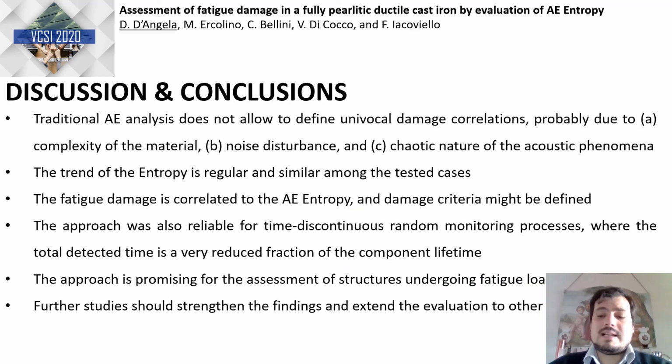Finally, we can discuss the results and trace the conclusions. We didn't show the results related to the acoustic emission analysis, but we can say that they didn't allow us to define a univocal damage correlation. This is probably due to the complexity of the material, the noise disturbance, as well as the chaotic nature of the acoustic phenomena. We saw how the trend of the acoustic entropy is regular and similar among the different tests, despite the completely different basic acoustic emission exhibited, as well as the different testing conditions.